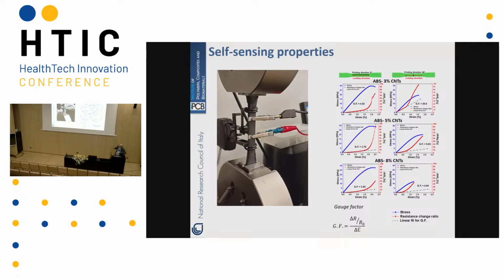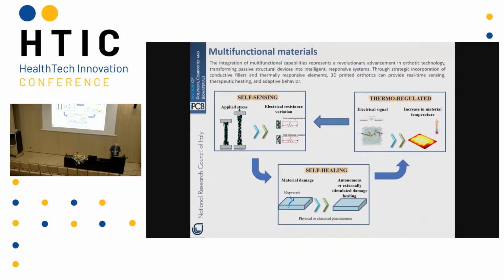As you said before, you can also follow the tension inside your sample by following the electrical conductivity of your sample. It is a very simple experiment in which you can follow the deformation of your sample from a mechanical point of view and the change in the electrical properties. It follows more or less quite well up to the elastic deformation. After that, there is some plastic deformation that is not recovered, but time to time this deformation is enough for our scope. Okay. So by changing materials, you can apply different functionality and improve your results.